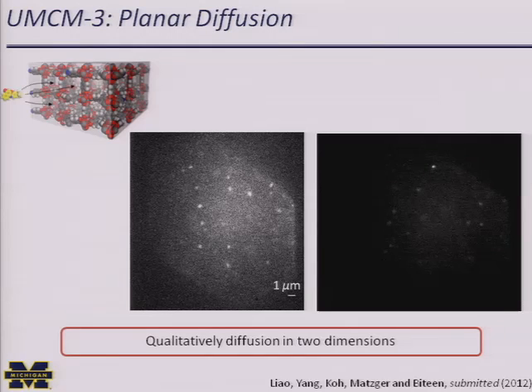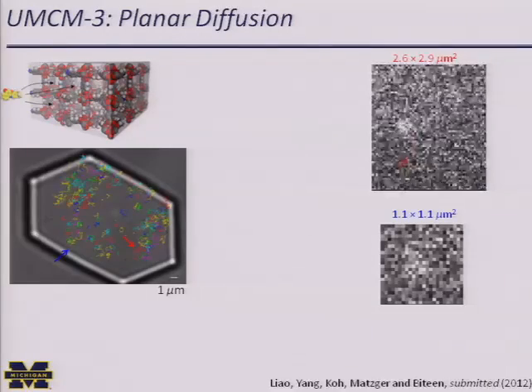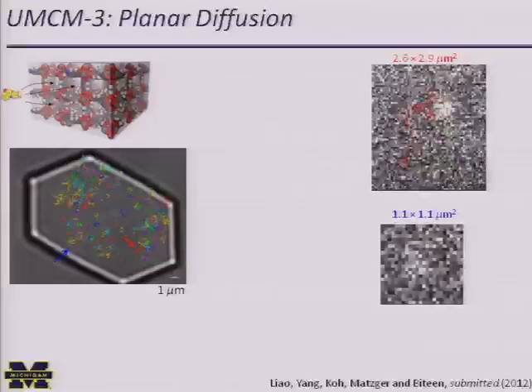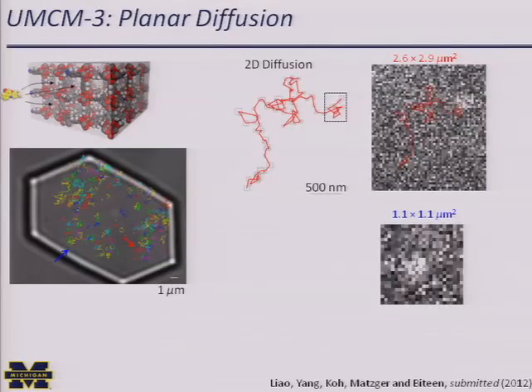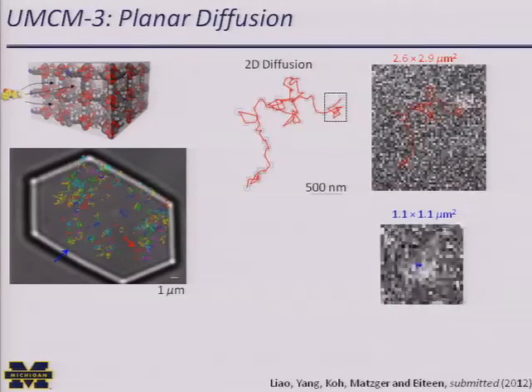Finally, in UMCM3, we see planar diffusion along these planes here. And so we see long trajectories. The molecules can't come out of focus once we find them in focus. And they're diffusing freely in 2 dimensions. Most of the molecules have this free diffusion, whereas, again, we see some highly confined molecules.